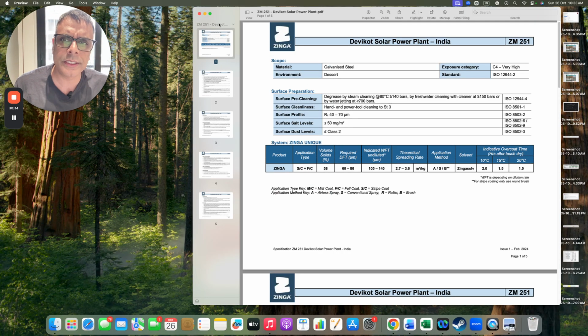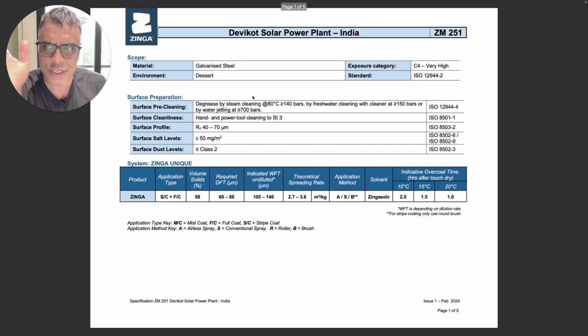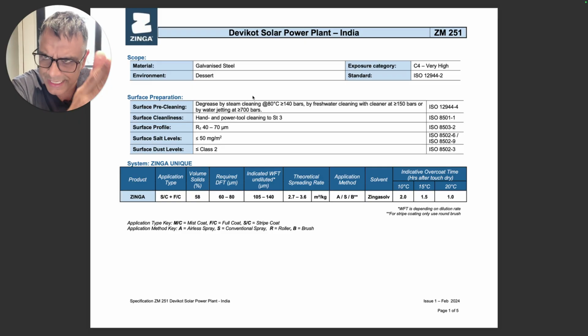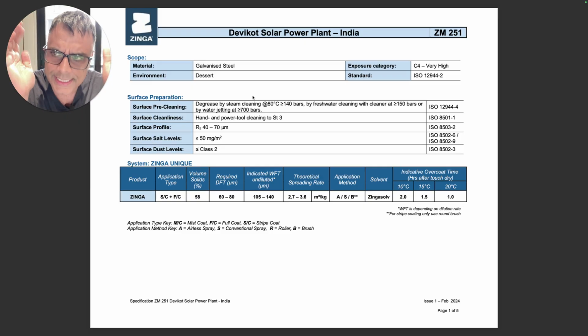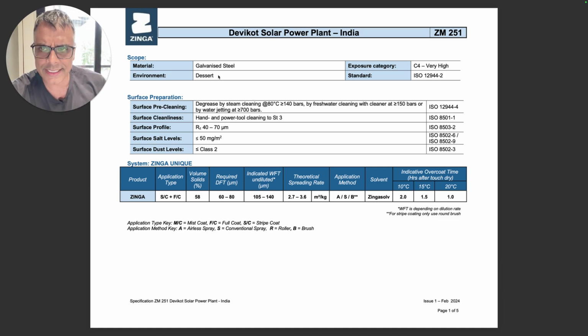Along with that, what we do is, once we go to a site, we will check the conditions, and then through Zinga Belgium we develop a coating system. And this coating system talks about your surface preparation, your application, your precautions. So Devikot was one site in Rajasthan, and what we realized, it's galvanized steel, it's a desert environment, exposure category is C4, very high, and we said that surface preparation is needed. Zinga unique system is required, and you can see the required DFT and the spreading rate, application method, and overcoat, touch dry, everything is mentioned.